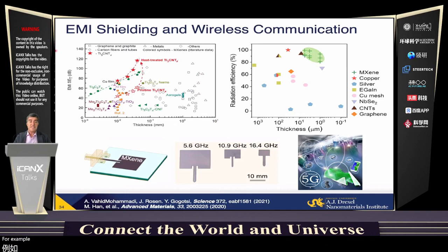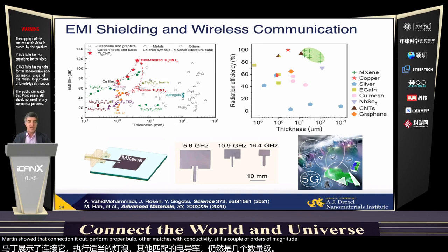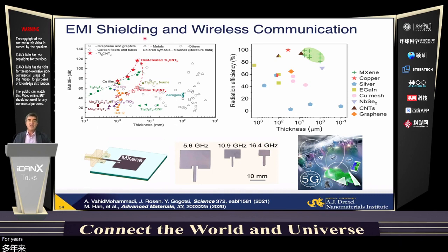For example, MXenes have been very efficient materials for electromagnetic interference shielding. Traditionally, it was considered that metallic conductivity is really the key for shielding electromagnetic fields and protecting our electronic devices from noise, from being read by adversaries. And MXene shows that it can actually outperform copper, gold, other metals with conductivity still a couple of orders of magnitude higher here. It really opened a new field of science for EMI shielding, or in general electromagnetic field interactions with 2D materials